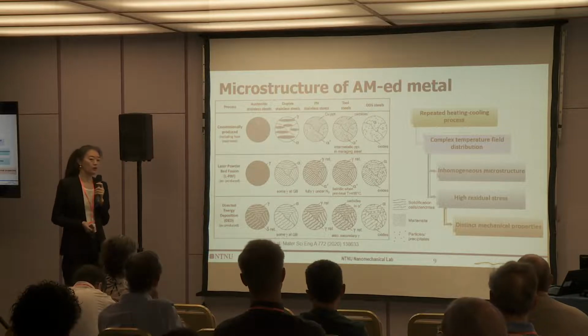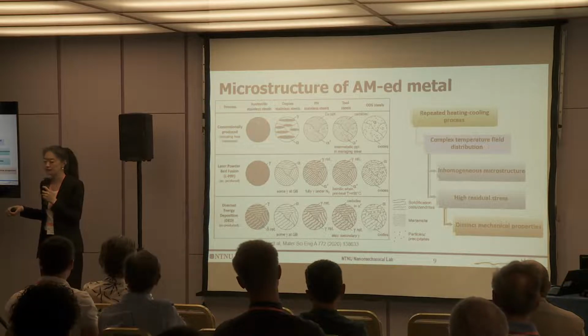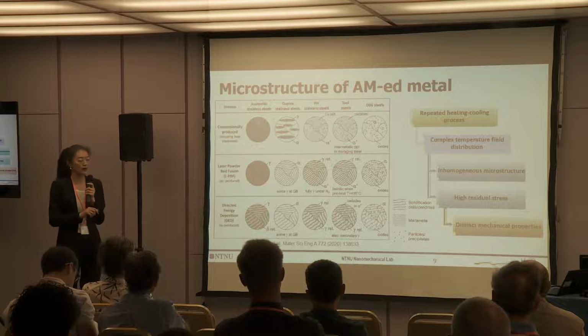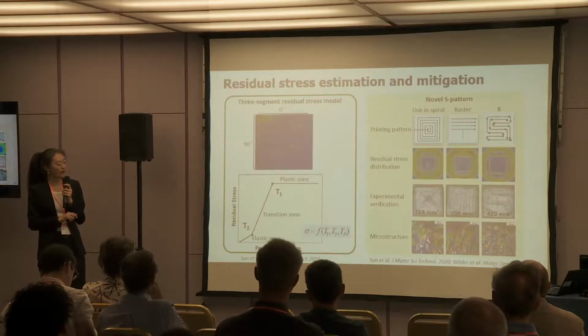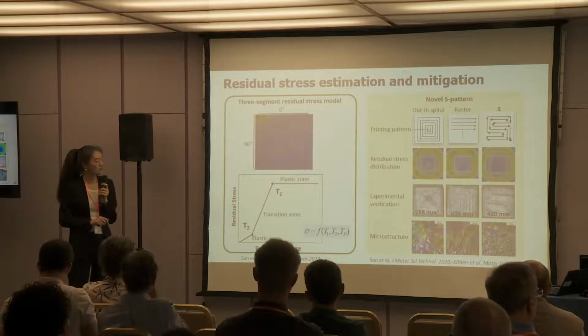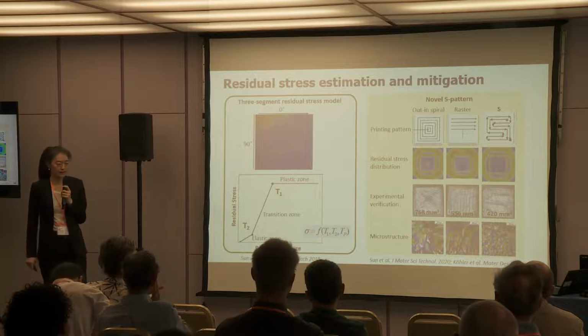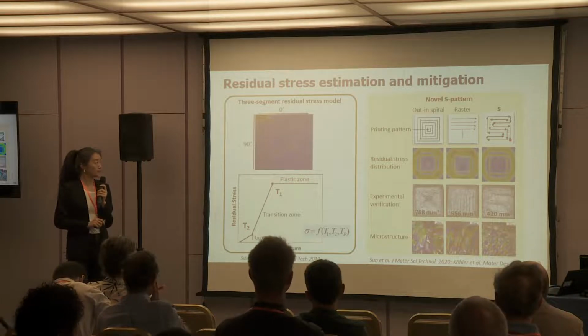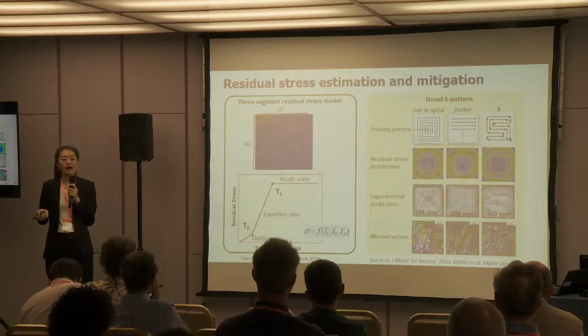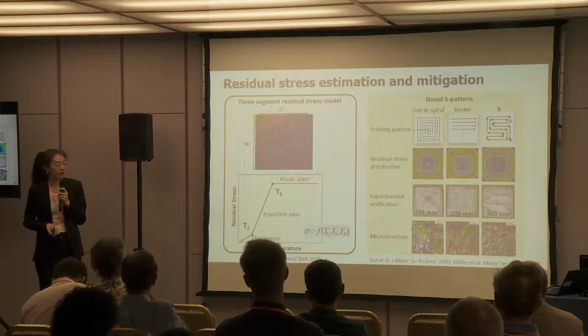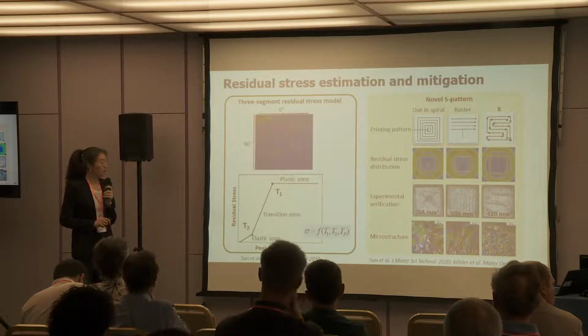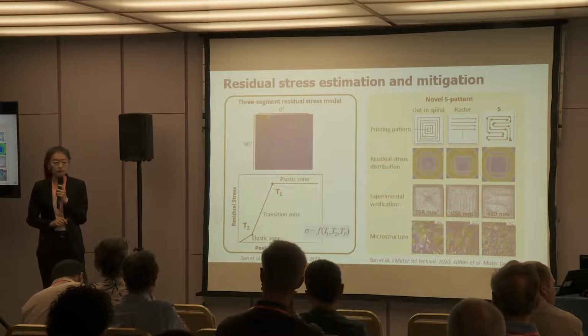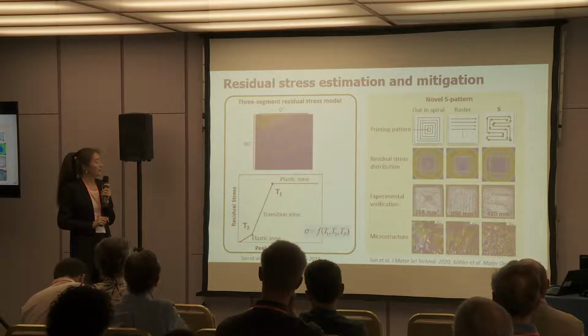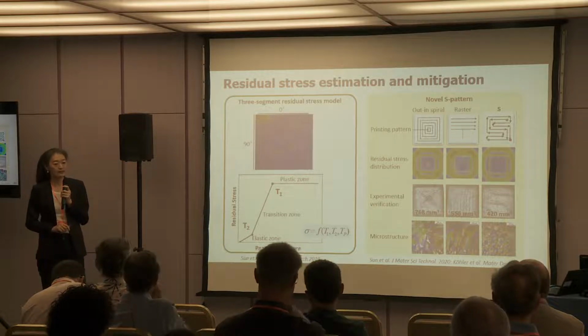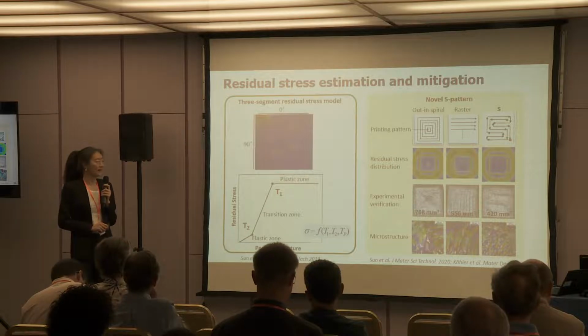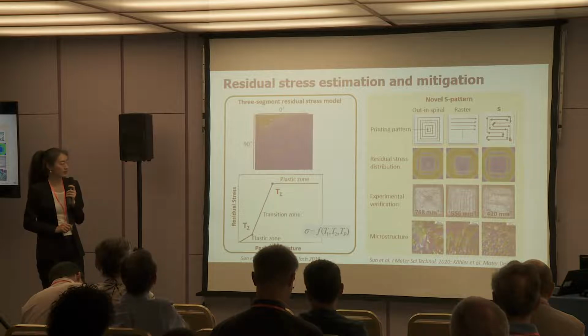And previously, people used conventional mechanical characterization methods to analyze the fracture, fatigue, creep, and other properties of AM-ed materials. And our group has also put a lot of effort into this field. Here are some highlights about AM-related research in our group. First is residual stress estimation and mitigation. Of course, due to the very high temperature gradient, residual stress is almost unavoidable in the AM process. Often high residual stress has a detrimental effect on material performance. So if we can well predict and mitigate the residual stress, then we solve a big problem in the AM field. And there we have proposed the 3-segment residual stress model.